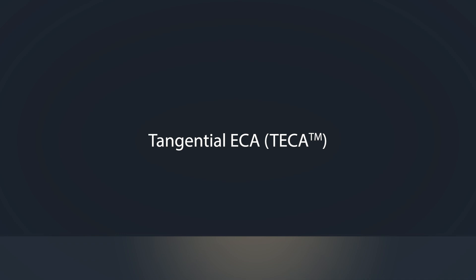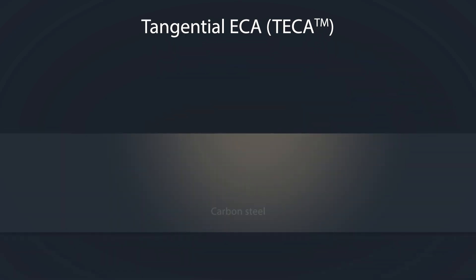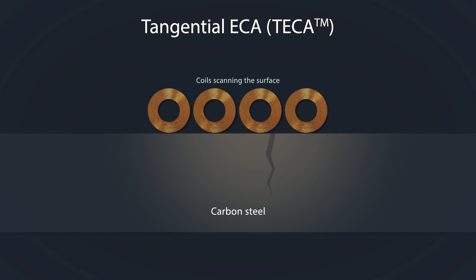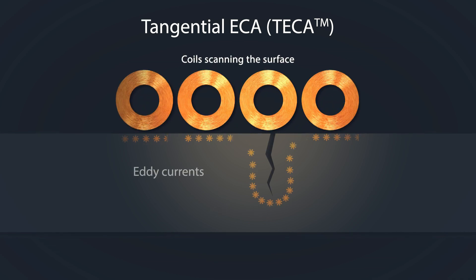The Shark probe incorporates a new technology called Tangential Eddy Current Array, or TECA. In TECA, coils are positioned on their sides, their central axes parallel to the surface. In this configuration, eddy currents flow parallel to the surface, where they dive under cracks and rise back to the surface, enabling accurate depth measurement.